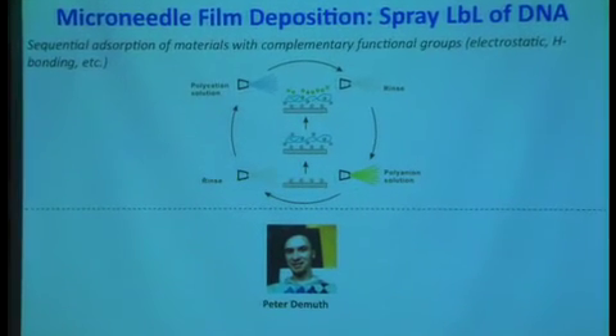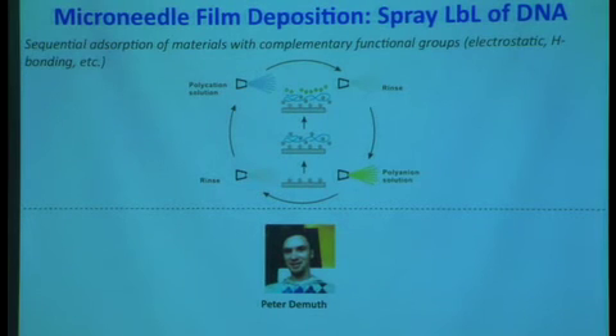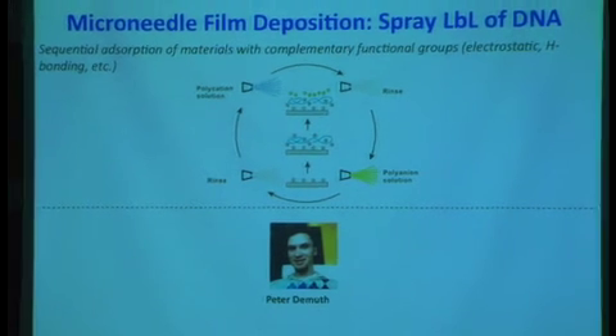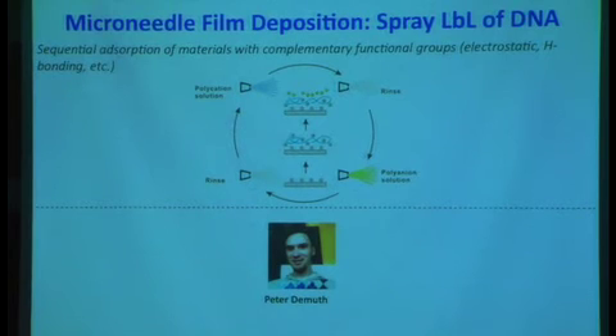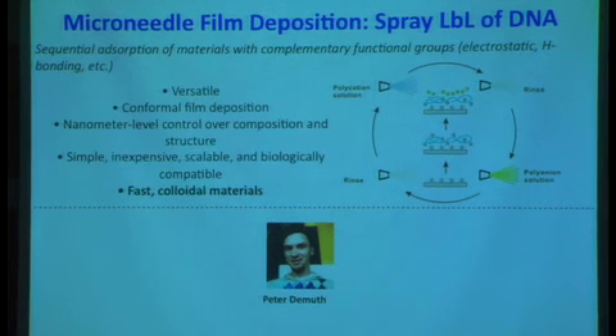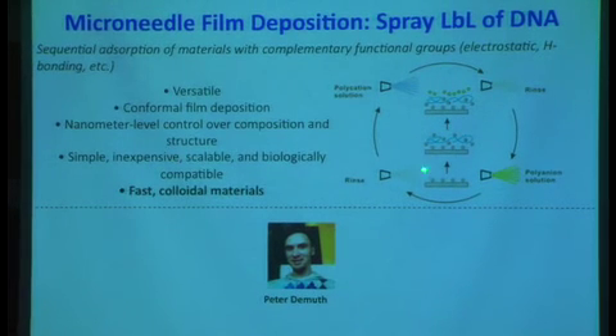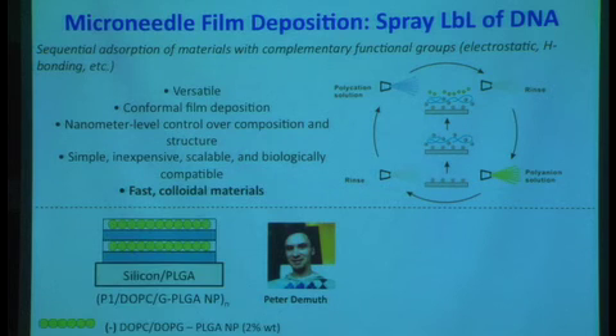Now we can go back to the spray layer by layer technique and use it to coat a fairly complex surface. We'd like to get beyond the stratum corneum, and one way of doing that is to use microneedles, a technique that was developed by Mark Prausnitz, who's now at Georgia Tech. So the idea here is that we can actually put down these thin films, insert them with the microneedle into the mouse ear or into the skin, and that when you remove the stamp or the microneedle, you will retain a thin film that will deliver the vaccine over time.